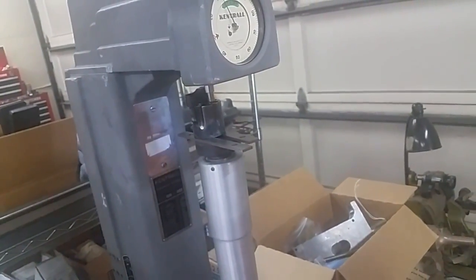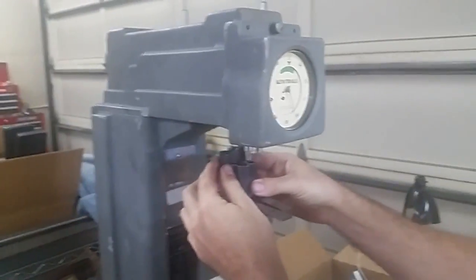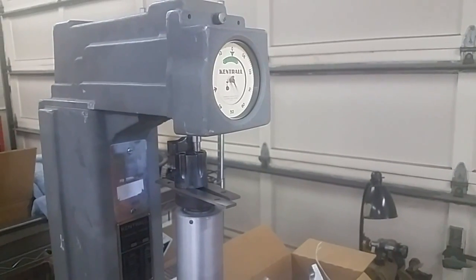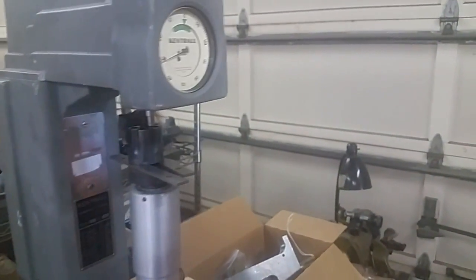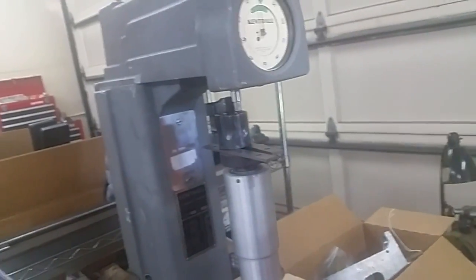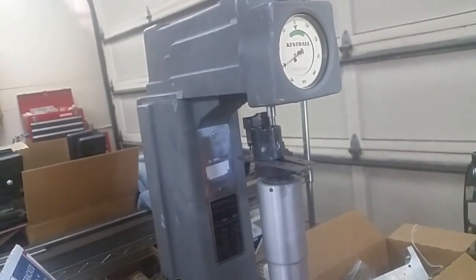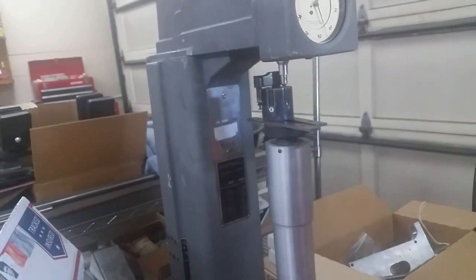Nine? It can't be right. Even dead soft would be in the teens, wouldn't it? Yup, should be. That's why I don't trust the test - it's compressing the shims and it's not supported well. 31. 31 is better, probably closer to a real number. Any deviancy is going to error on the side of soft, right? 30. Errors are to the soft side usually.